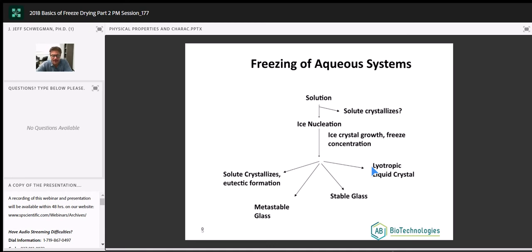Lyotropic liquid crystals. This is something I've worked through my entire career. We've only worked on one product that demonstrated liquid crystal characteristics. So we're not going to focus on that. It's basically a system that shows some order in its structure, but behaves more like an amorphous phase. So these three are going to be the ones we're working on. 75% of the formulations we've worked on for clients at our facility have been either a glass, a stable glass, a eutectic, or a mixture of both, 75%. 25%, we do see the metastable glass where we would need to talk about adding an annealing step to get rid of that.